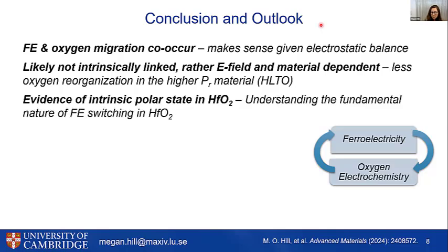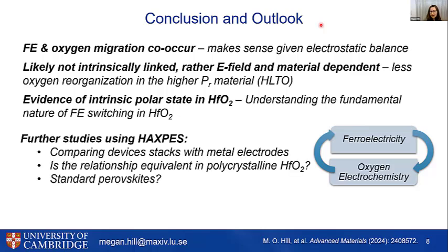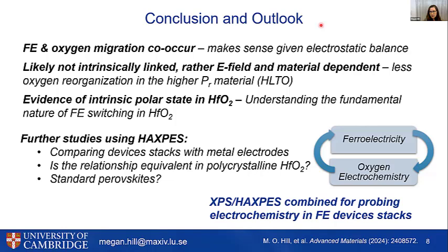So from this, we think that we're providing evidence of an intrinsic polar state in hafnia, better understanding the fundamental nature of this material. And we think that HAXPES could be used in a similar way with other types of device stacks, like ones that have actual metal electrodes on top, or to study similar polycrystalline material of hafnia, which is very interesting to the ferroelectrics field, or standard perovskites as well. But ultimately, this combination of XPS and HAXPES allowed us to probe different depths and better separate the effects of ferroelectricity and oxygen electrochemistry. And I think that many researchers could benefit from this same type of experimental design.